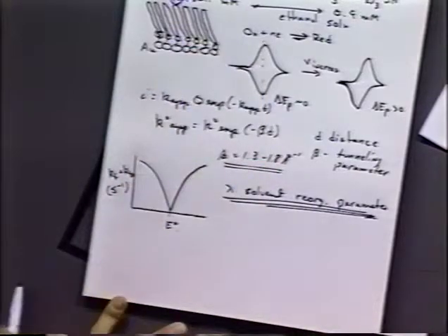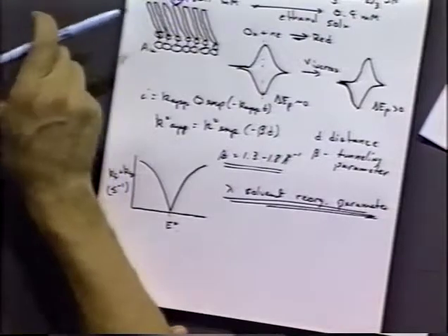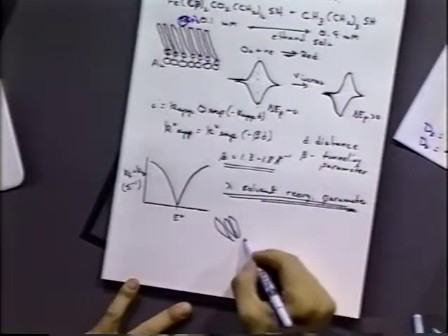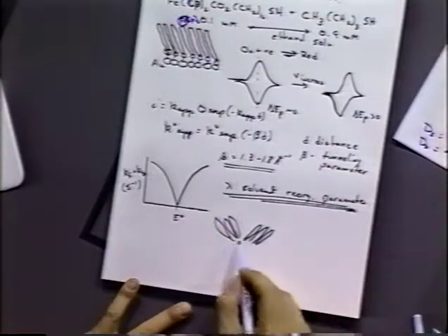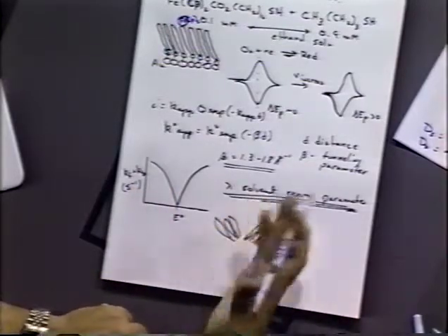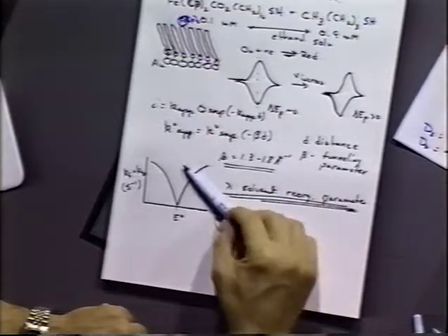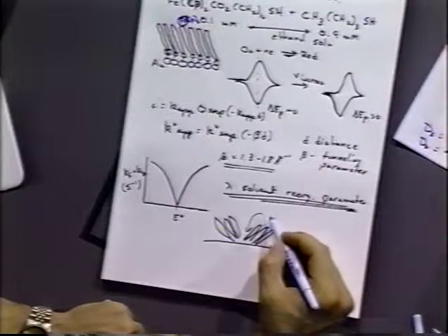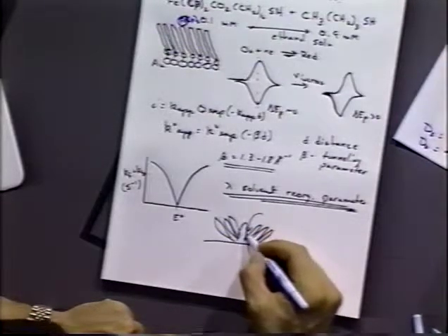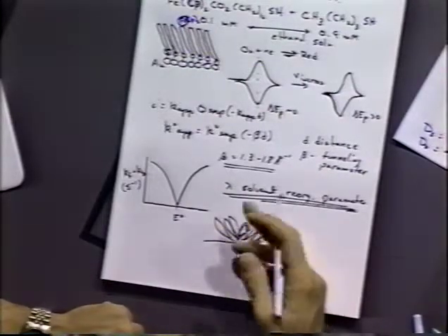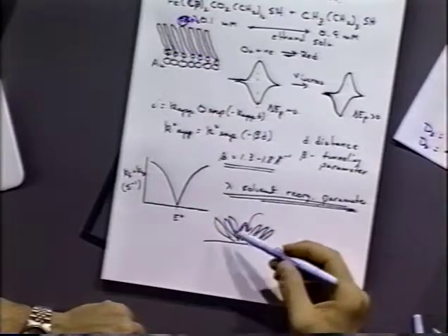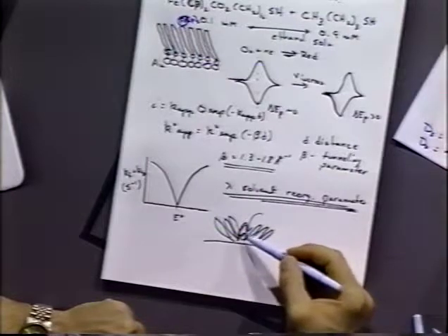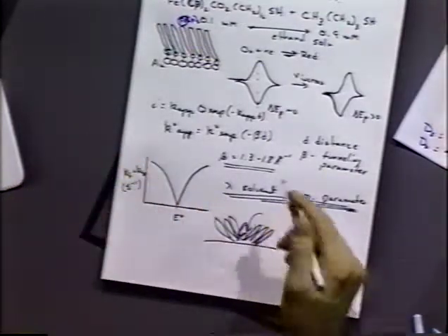One thing with this experiment that's kind of tricky is the presence of dislocations or disorganized film will really screw these experiments up. You can think of the films being associated in these laying down forms but there can be what they call phase boundaries where some of the things are laying in this direction and then there's a boundary where they're all laying in the other direction. In that particular case, there is now a hole in the layer where the ferrocene can be laying down inside that film and so it'd be very close to the electrode surface. So that really changes the rate of electron transfer much more rapidly now. So even a small percentage of these very rapid ferrocene holes in the surface or dislocations will cause the rate to be much different.